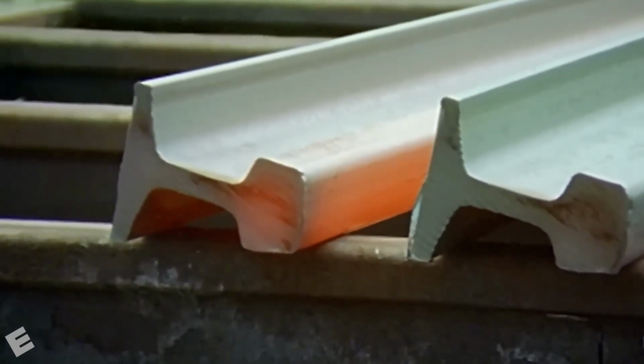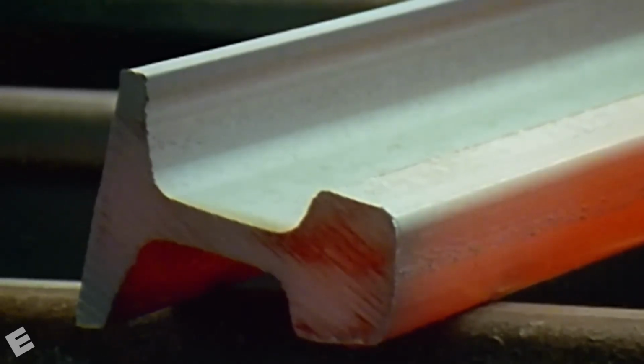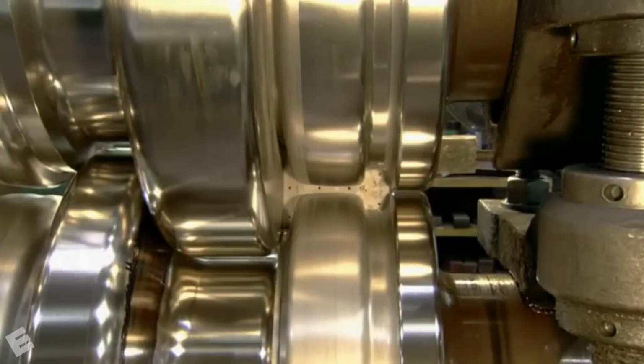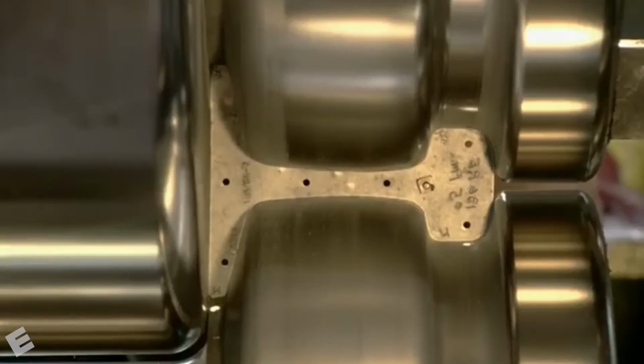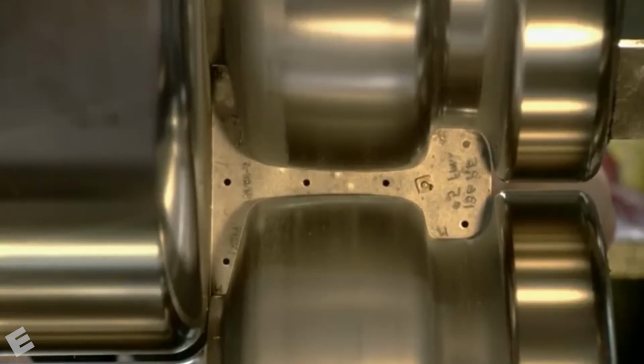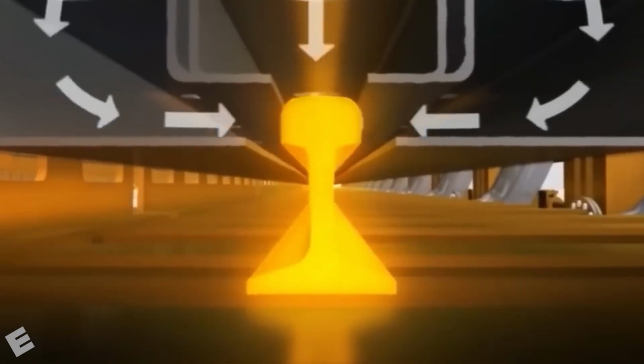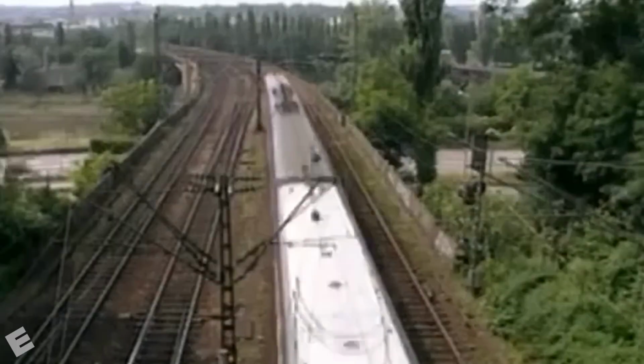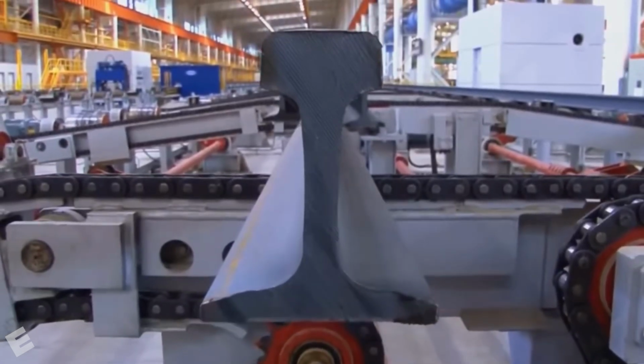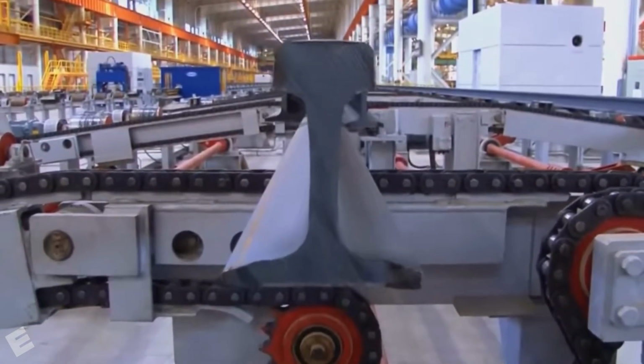For heavy-duty track, the railhead may be heat-treated while still hot from rolling. In voestalpine's head hardening process, the head is cooled under carefully controlled conditions. This changes its microscopic structure and hardens the running surface deeply. The result is greater resistance to wear and rolling contact fatigue, especially on curves and heavily loaded routes. It does not eliminate friction, it helps the rail retain a smooth shape longer.